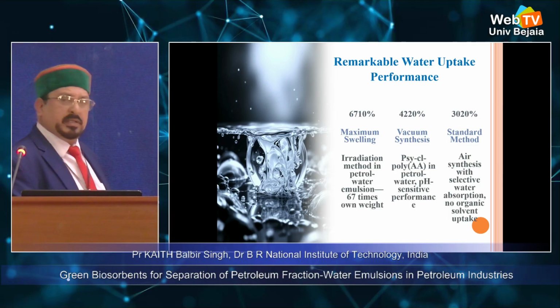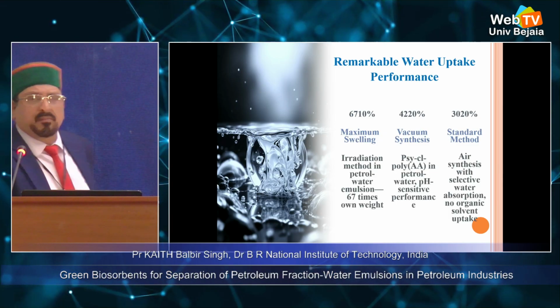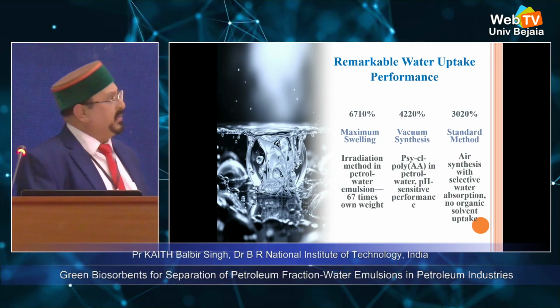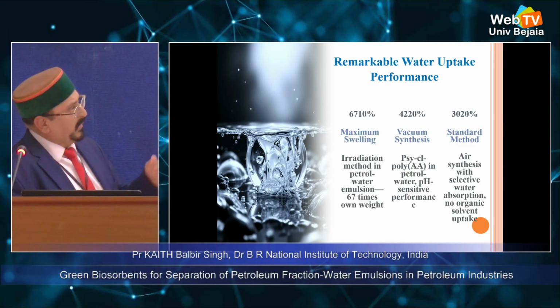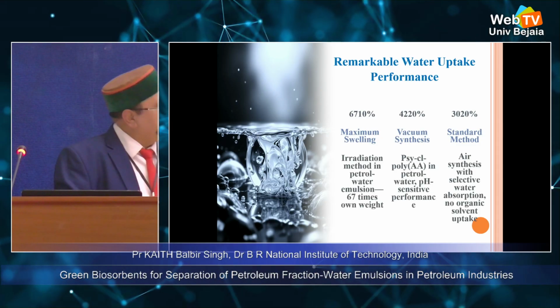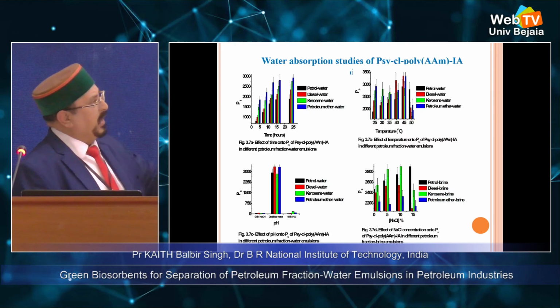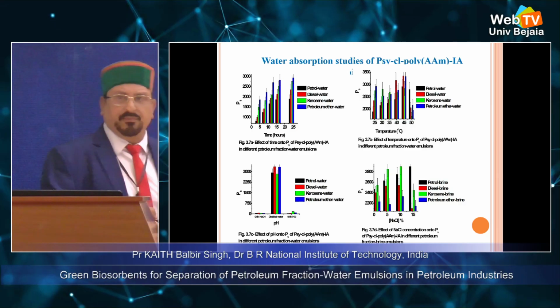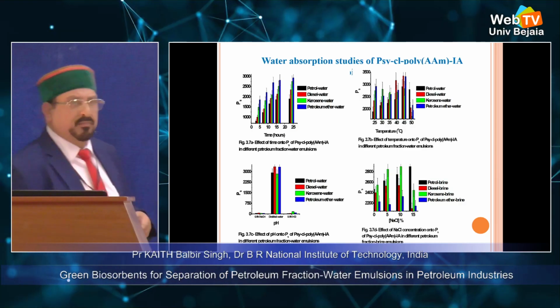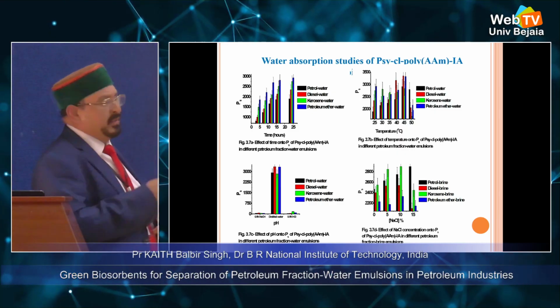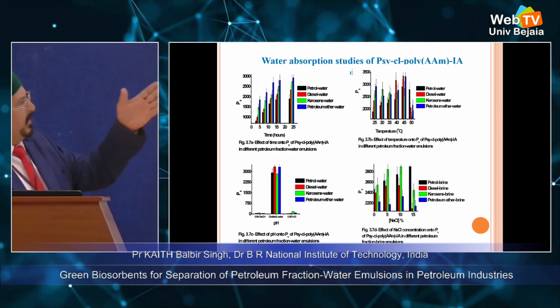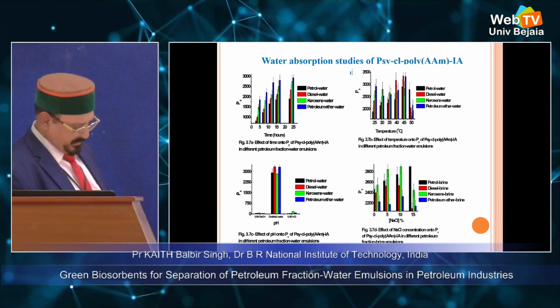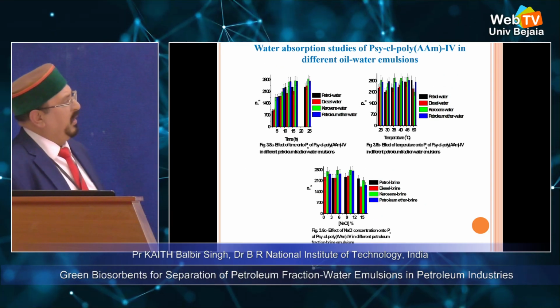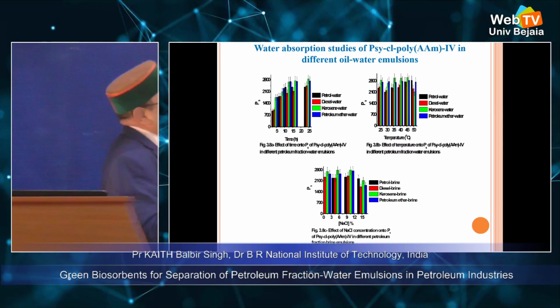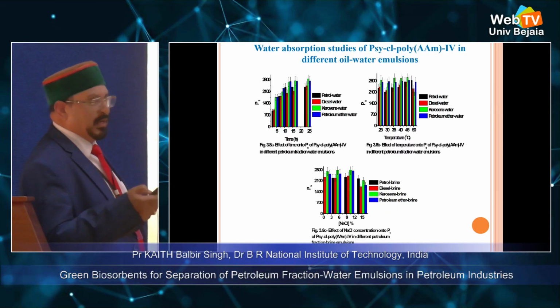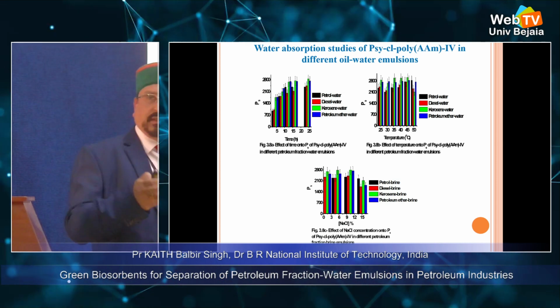The remarkable water uptake performance was shown by the material which we prepared under the impact of gamma radiations, followed by vacuum synthesis, and then the standard method in air. And these are the results of my own lab. You can see we used different emulsions like petroleum ether, kerosene, diesel water, and other petroleum fraction water emulsions. These are some of the results which we got during the experimentation, and we got very good results, and very effectively we could separate different petroleum fraction water emulsion fractions.